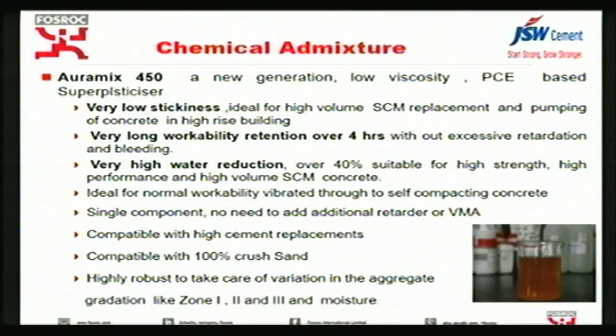Just to brief about our admixture, what we are using, it is a PCE-based admixture, a new generation admixture. It gives very low viscosity and very low stickiness. This kind of admixture is ideal for supplementary cementitious replacement like high volume slag, even from the point of pumping, and very long workability. We have already done it, we can easily get beyond 4 hours workability retention without any slump loss.